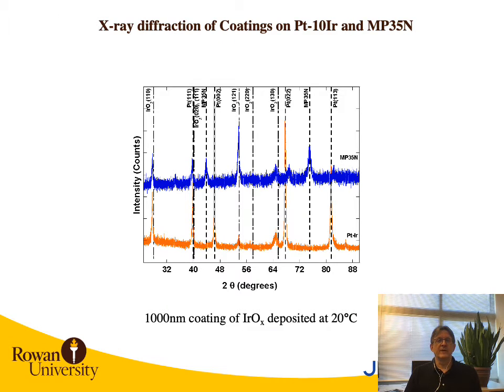On this slide are the X-ray diffraction spectra for the thickest coatings from the last slide. If we look here, the lower curve represents the coating on platinum 10 iridium. The upper curve represents the coating on MP35N. If we focus on the iridium oxide peaks where there are no substrate peaks, for example here, the 110 peak, you'll see that the texturing in that orientation seems to be a little better on the platinum 10 iridium. Alternatively, if you look here at the 121 peak, the texturing seems to be better on the MP35N in that orientation than it is on the platinum 10 iridium.